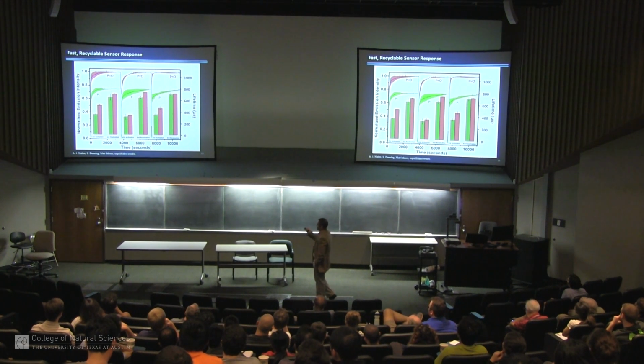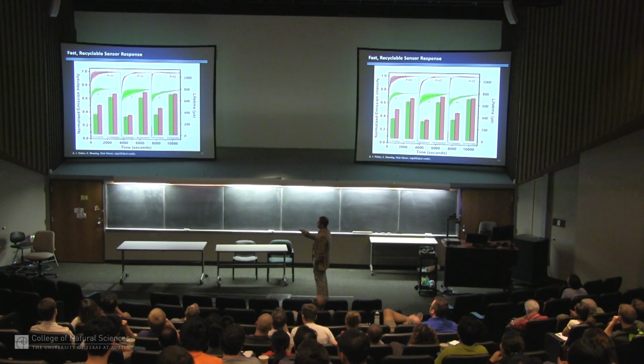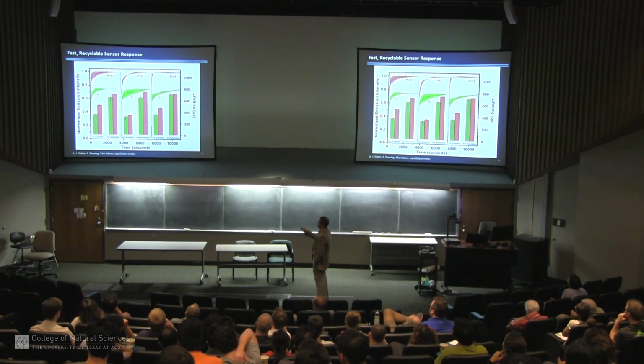And recently, Sam has worked with Matt Moore in the Holiday group to show really how fast this material acts as a sensor. So you can see the phosphine is always lower than the phosphine oxide, but actually these things switch on within a few seconds, and the luminescence intensity levels out. Then you can reactivate the material, it switches back onto the same level.